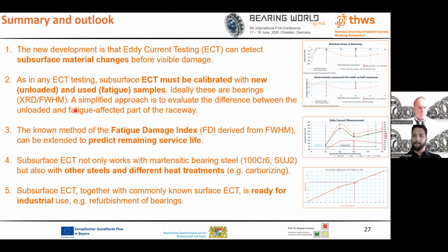A simplified approach is to evaluate the difference between an unloaded and fatigue-affected part of the raceway. The fatigue damage index, derived from FWHM, can be extended towards the prediction of remaining service life. In combination with ECT, this provides the basis for a non-destructive estimation of remaining service life.